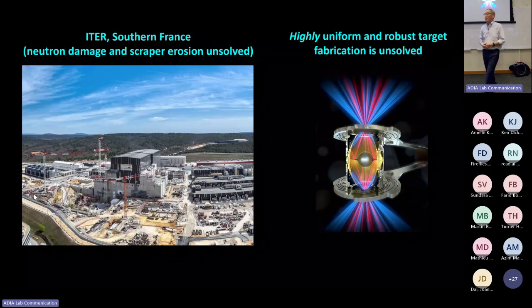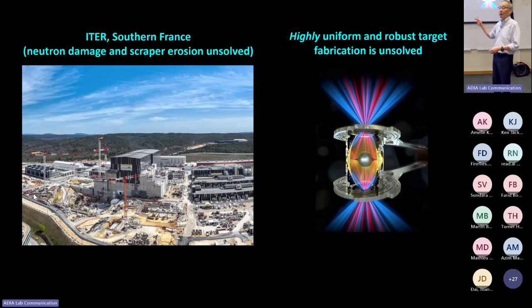So when you evaporate tritium and deuterium, it's polycrystalline, so you have to anneal it maybe half a dozen times. And so that takes a day to make one of these. And then it's suspended by atomically thin plastic films, 50 angstroms in thickness, in this hollow around this gold cylinder. And then you hand carry it very gently to where you're going to put it in front of this laser, and you lose half the targets because the thing breaks, this 50 angstrom thing. And so if this is going to become commercial, you have to shoot them in 20 times a second into something with a lot of gas and a lot of turbulence because of the previous nuclear explosion. And so it has some technical challenges.